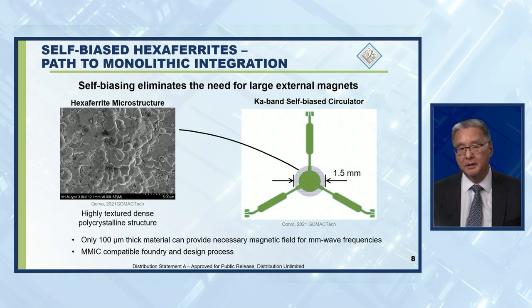The drawing on the right depicts an integrated Ka-band circulator that uses a 1.5 millimeter diameter disk of the self-biased material, which is now compatible with Ka-band phased array spacing.